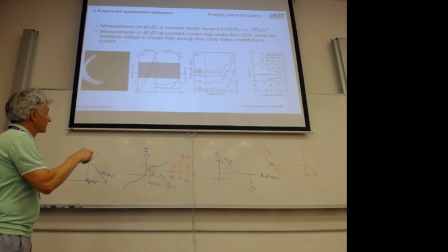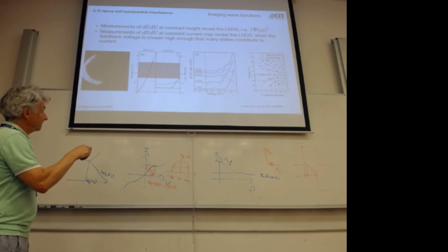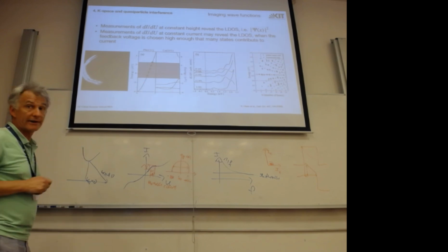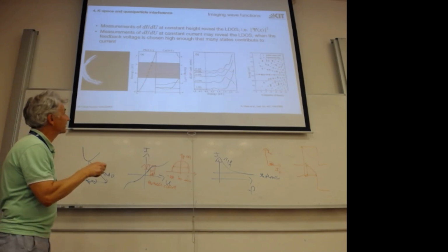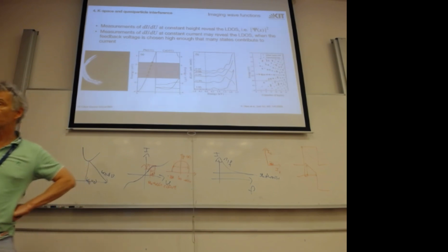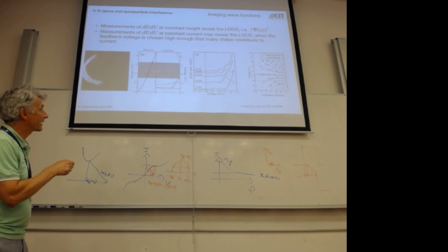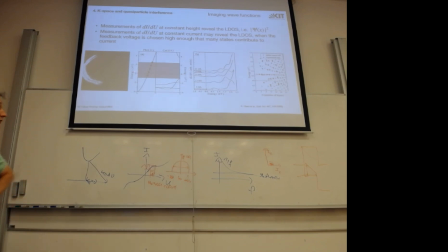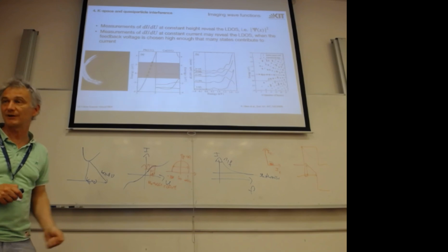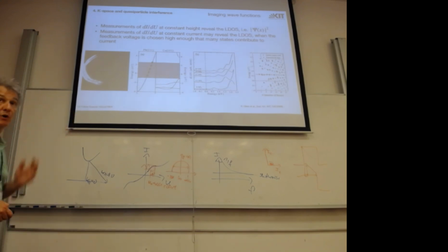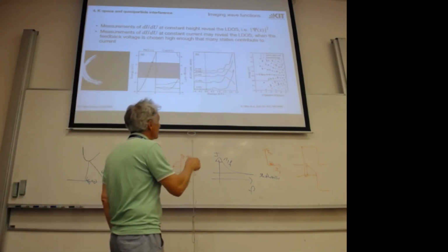Lead states cannot leave into the vacuum, they are reflected, but they can also not enter copper because there's a partial band gap in this direction. So they're bouncing back and forth. The electrons tunnel from the tip into this thing and bounce back and forth like a Fabry-Perot interferometer. Eventually they go out. They have some lifetime. So what we expect is these Fabry-Perot peaks here.